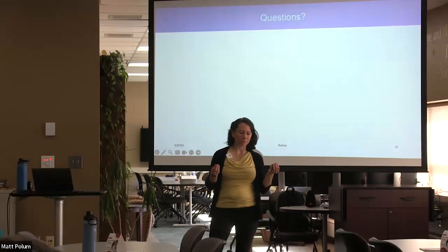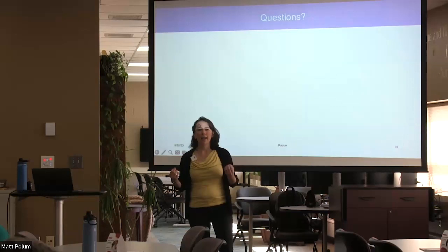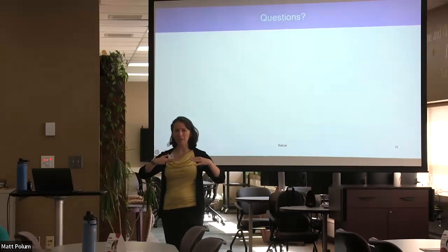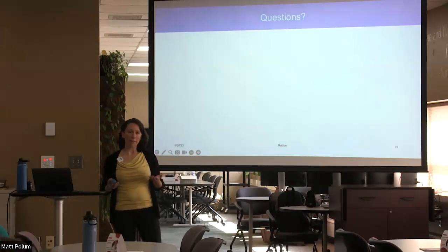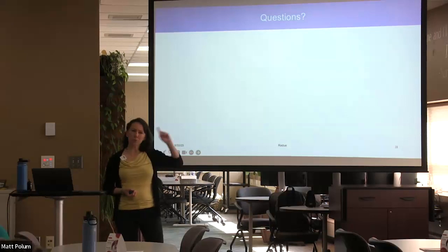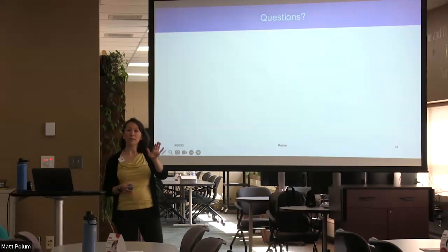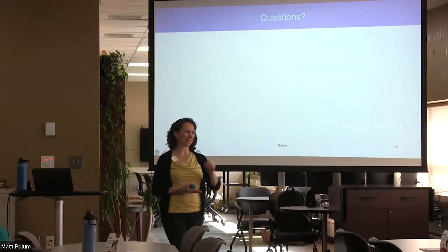However, Annika specifically is accounting for that, and she's measuring the glass sample by itself and then subtracting it from the data. So we're just dealing with a baseline. And then to answer your question, how confident I am that I'm measuring what I want to measure, I go to previous research that has measured this before, and check whether my peaks at least roughly match up with what's been done before. And yeah, we're dang spot on. So we're confident that we're looking at the right thing. Yes.